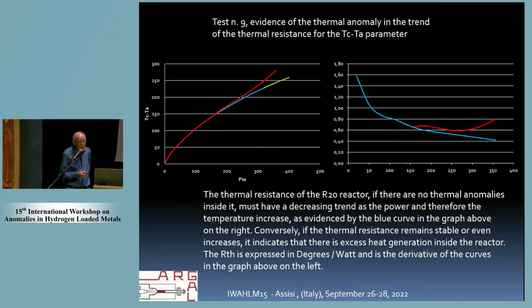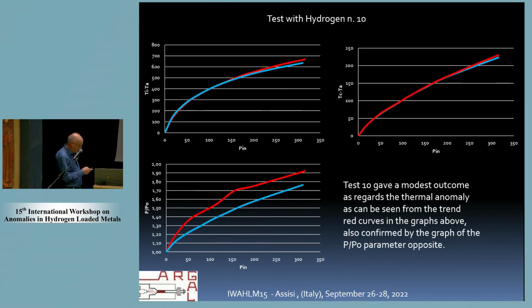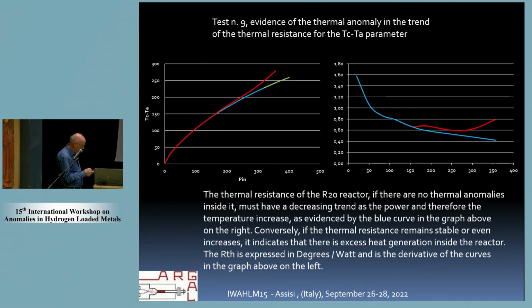I told before that we can have two methods to compare the curves: one is the overlapping of the curves from the experiment and calibration, or measuring the thermal resistance of the reactor. Here there is an example of the behavior of test 9, with the possibility to make the derivative of the curve of the temperature of the reactor. This is the thermal resistance calculated with a derivative of this curve here.